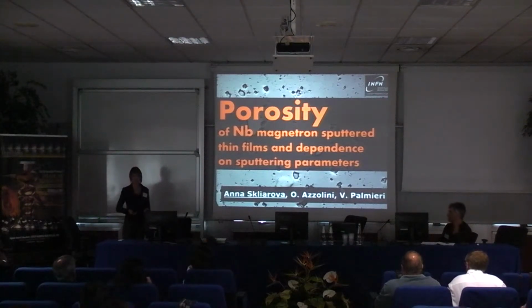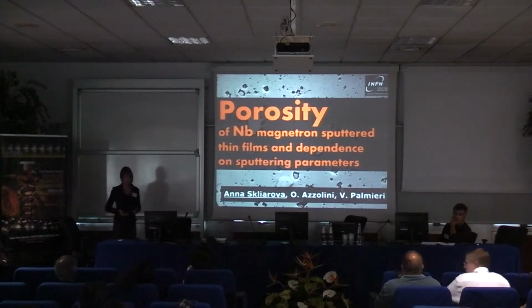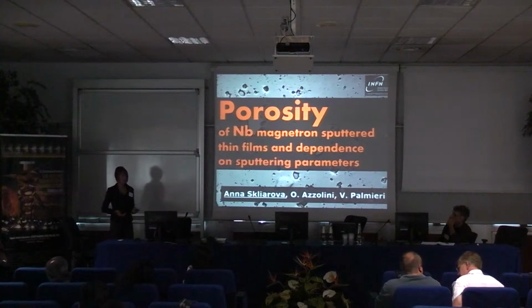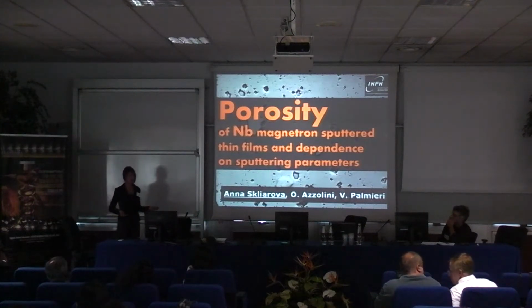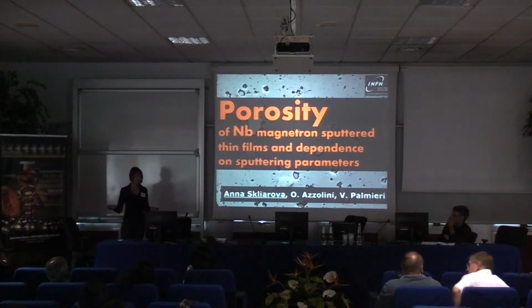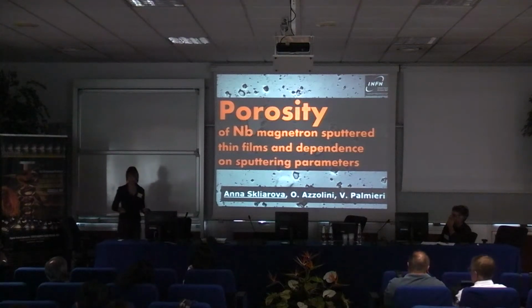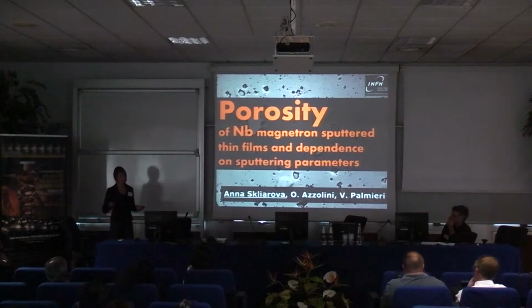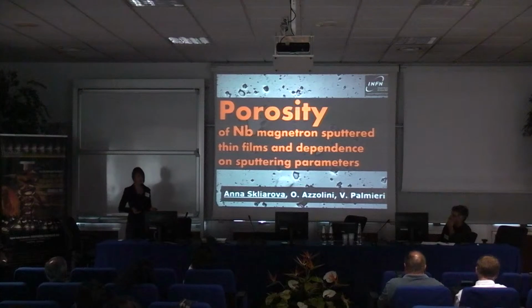Porosity can be originated by different reasons. For example, dust particles from the environment or metallic particles from the target or from the chamber can arrive at the substrate and be incorporated inside the film. And when the weakly bonded particle is removed, it leaves a hole.